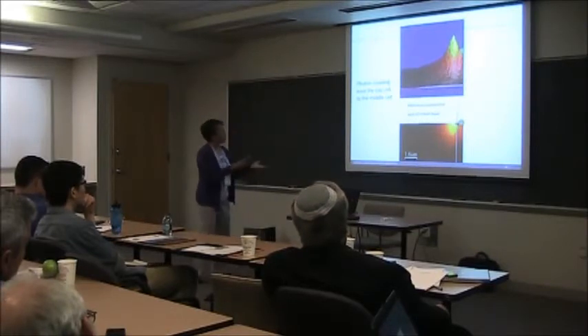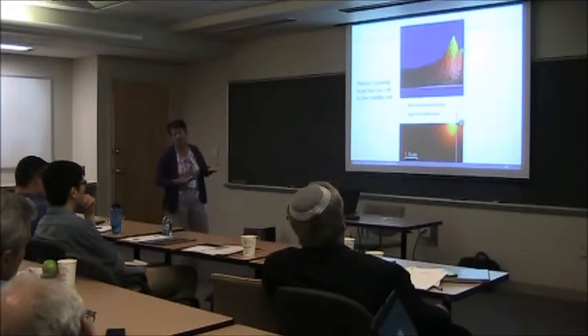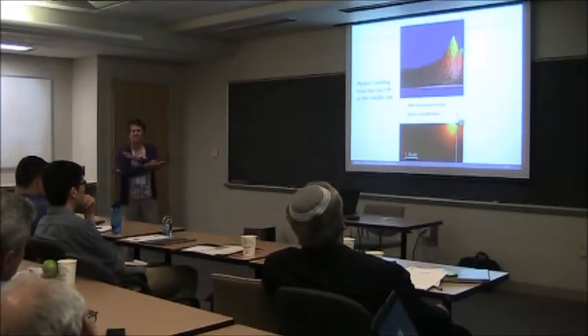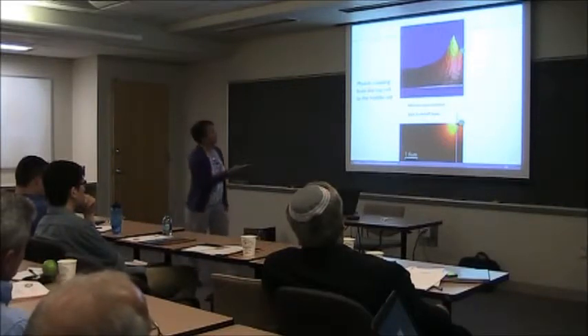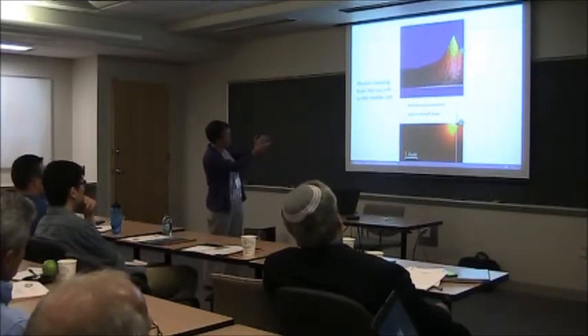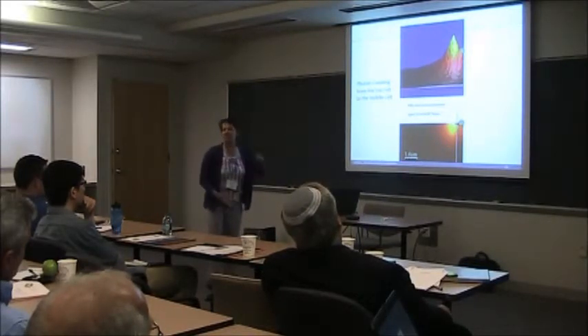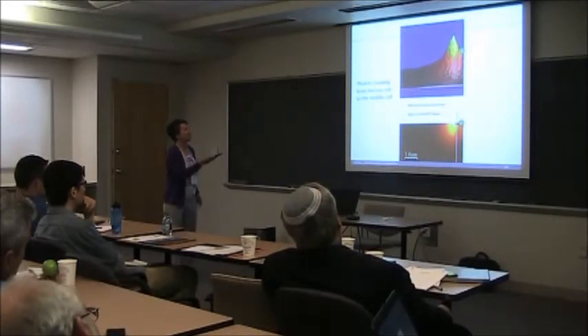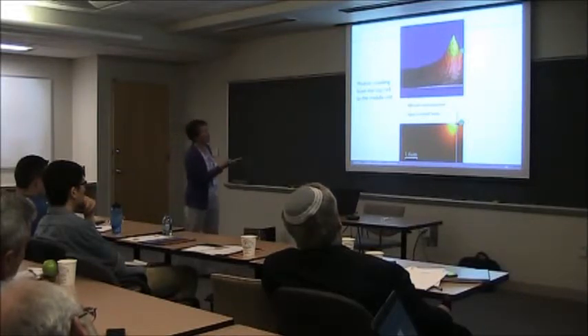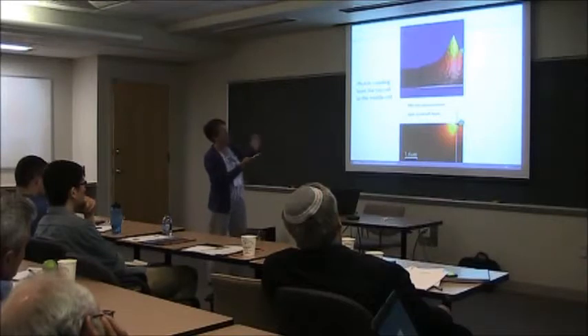If you put the beam, WSXM kind of flips everything, right? Those of you who have used it. So it's different than my physical layout. If I put the electron beam over here in the gallium indium phosphide, that's the wide band gap layer. I get luminescence, but what I'm mapping here is the gallium arsenide photoluminescence, 880 nanometers.